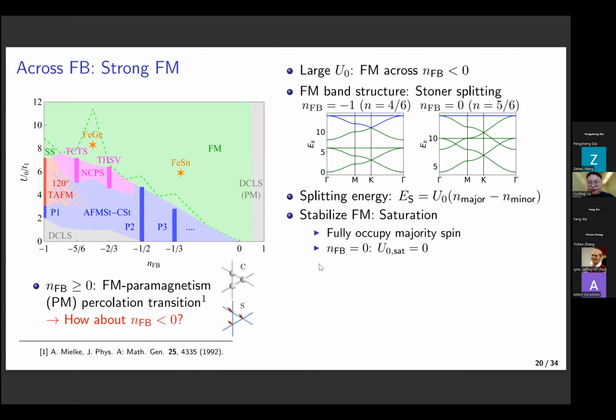So first, if we look at the half-filled flatband, we can see that as long as we have a finite splitting, we are lowering the spin majority bands below the Fermi level of the minority spin bands. So the saturation repulsion will be infinitesimally small. And as you can see in the phase diagram, indeed, as long as we turn on the repulsion, we already have the ferromagnetism, which is good.